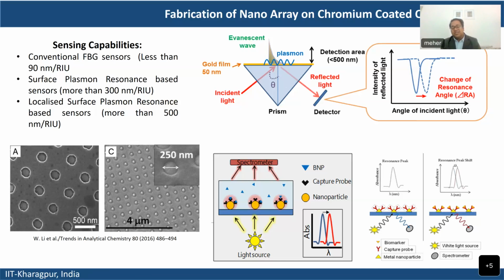So we thought, let us try localized surface plasmon-based sensors. Localized means we need to have patterns on the surface of the surface plasmon coating. For the surface plasmon coating, we generally use gold or some other material which is suitable for this purpose. And then we make very small features, you can see this is around 500 nanometers, and this is around 250 nanometers in diameter for these trenches. These are the nano trenches, holes basically. And then good sensitivity can be achieved.